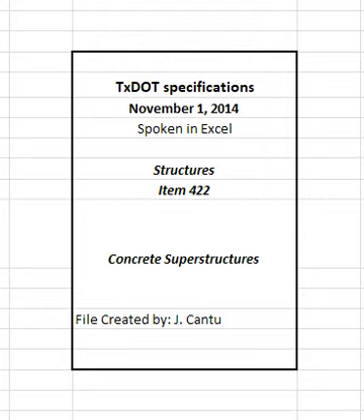Maintain the temperature of the top surface of bridge slabs and top slabs of direct traffic culverts at 50 degrees Fahrenheit or above for 72 hours from the time of placement and above 40 degrees Fahrenheit for an additional 72 hours. Use additional covering, insulated forms, or other means and, if necessary, supplement the covering with artificial heating. Avoid applying heat directly to concrete surfaces. Cure as specified in Section 422.4.8, Final Curing, during this period until all requirements for curing have been satisfied.